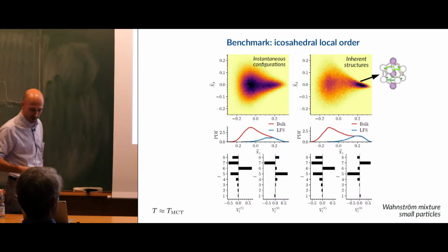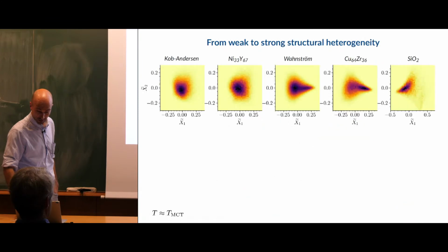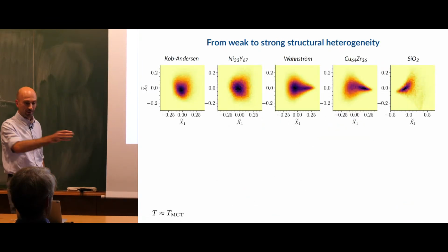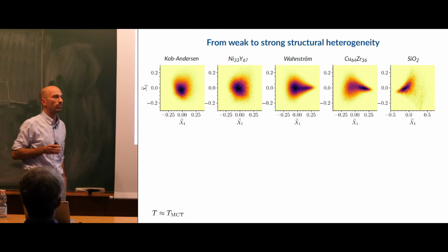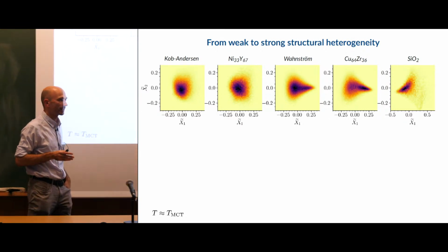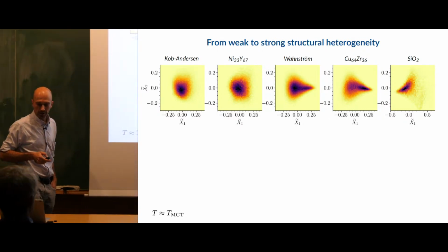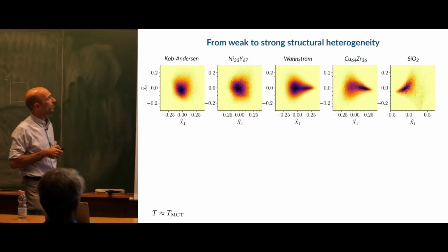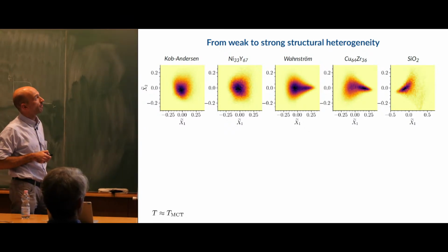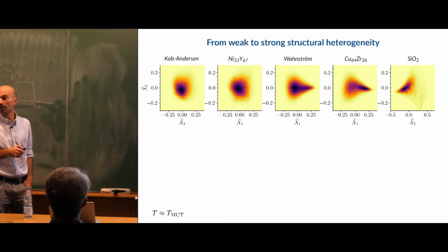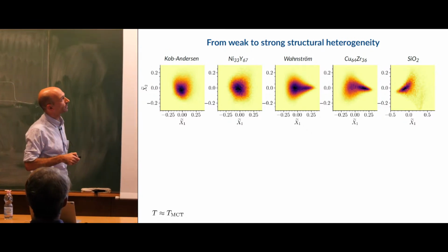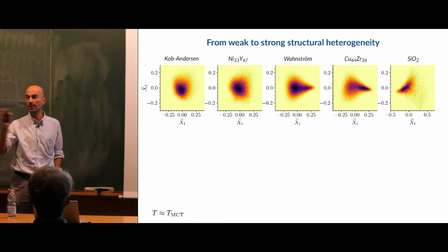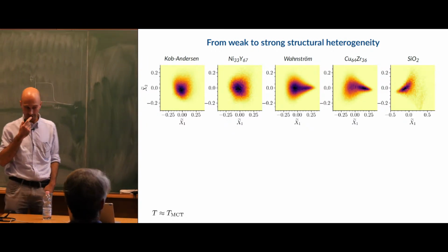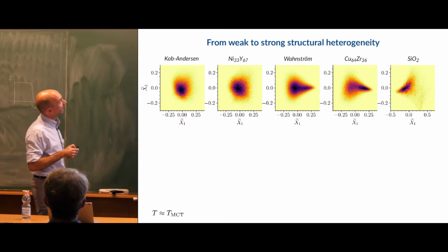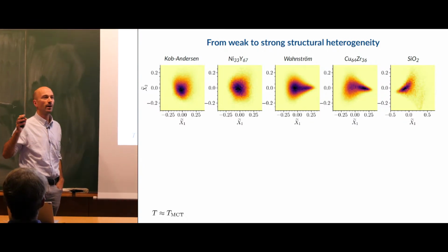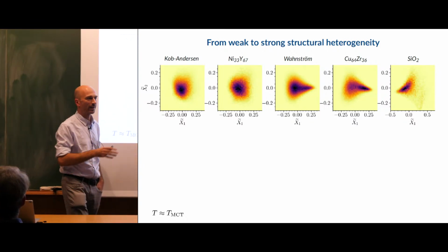Okay, so now that we are confident that the method works, we can explore a broader pool of computer models of glassy binary mixtures. And here we not only consider simple Lennard-Jones mixtures, but also more realistic models of metallic alloys like copper zirconium, as well as a model of amorphous silica here. So we have a range of very different binary mixtures. And as we go from left to right, we see some sort of gradient, some sort of progressive change.